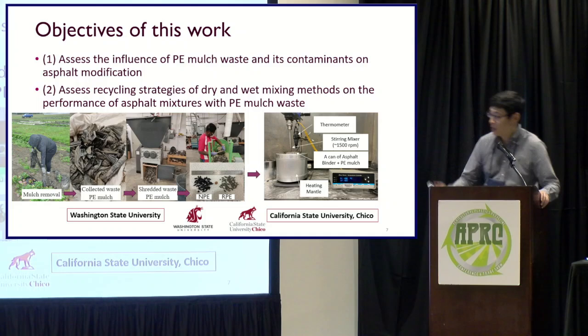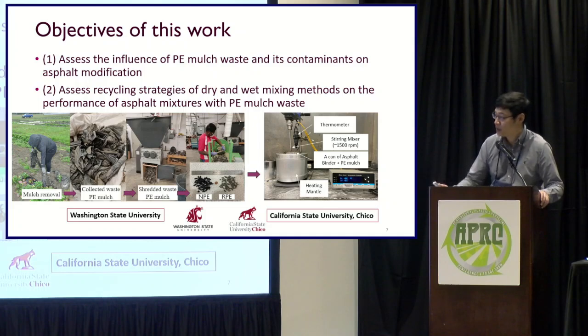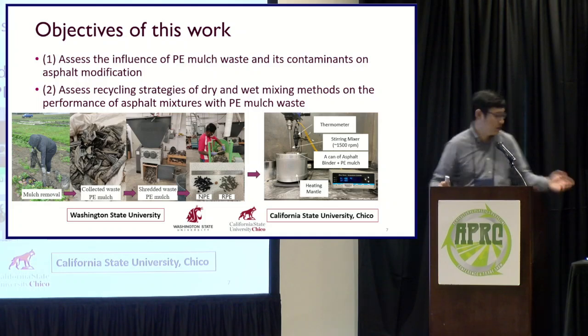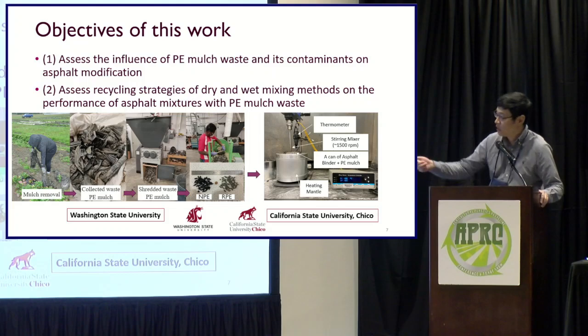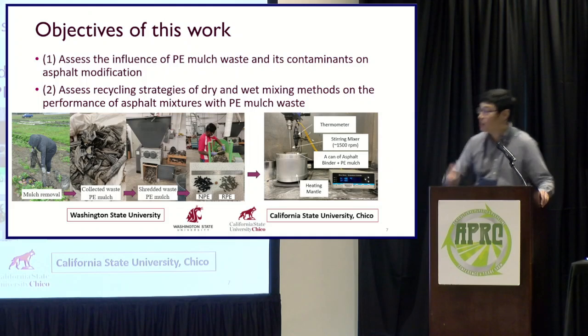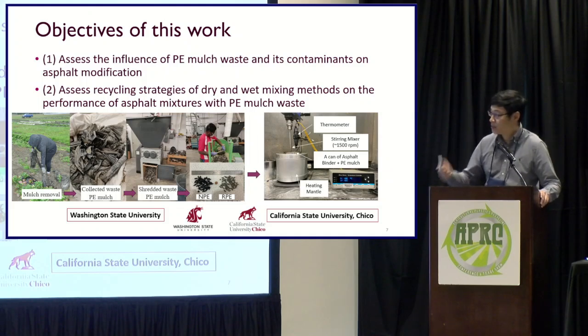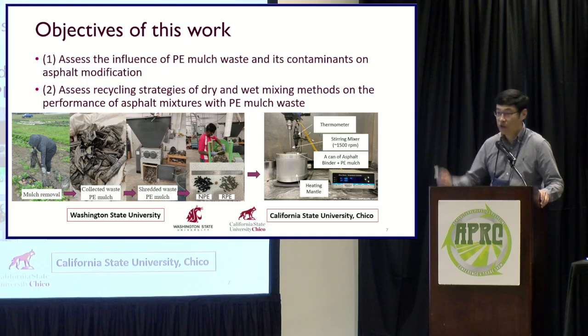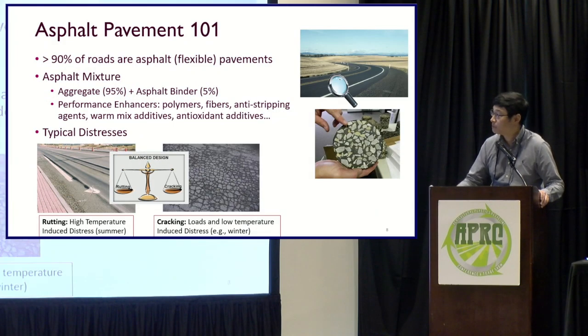So here is a close collaboration with Washington State University. Karl and his team helped to process the pellets and then ship them to California State University here. So we ran the blending in the lab using this heating mantle at a temperature of 170 degrees Celsius, blended the pellets with the asphalt and produced the plastic modified asphalt and used it in the lab.